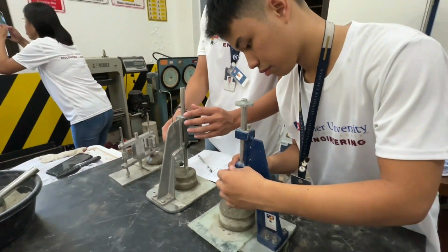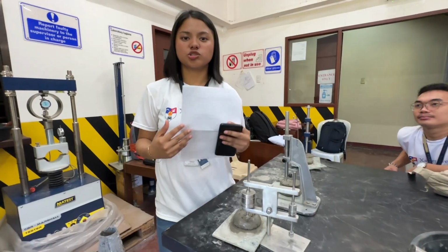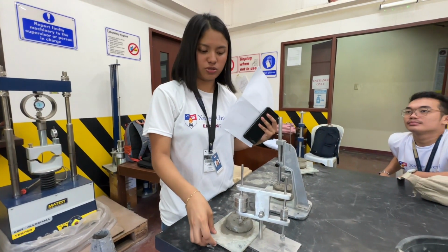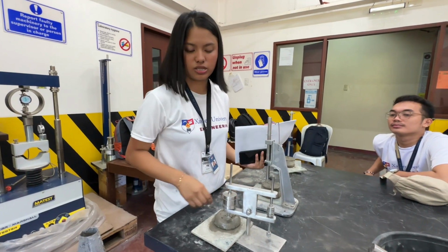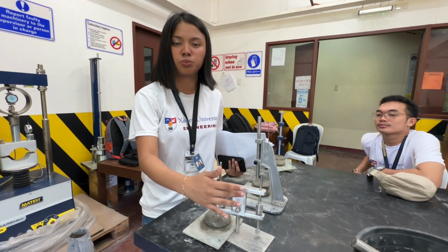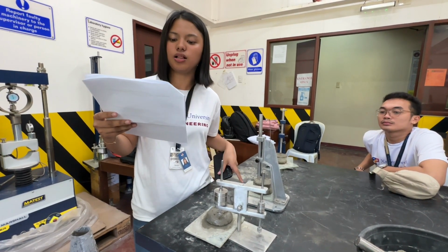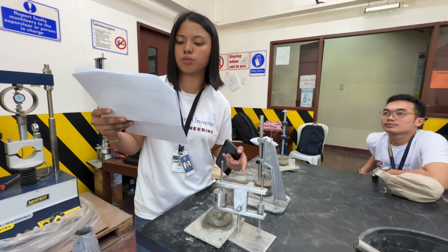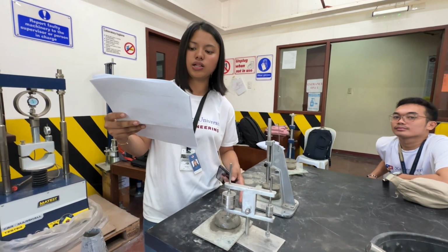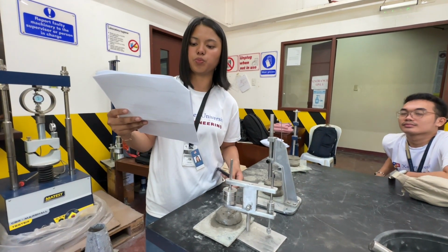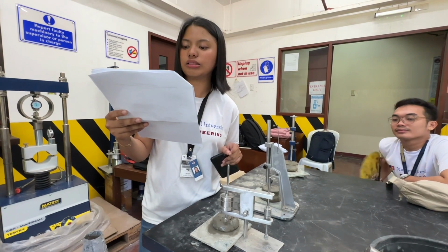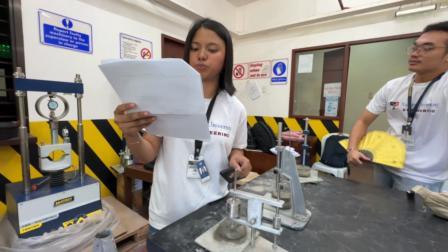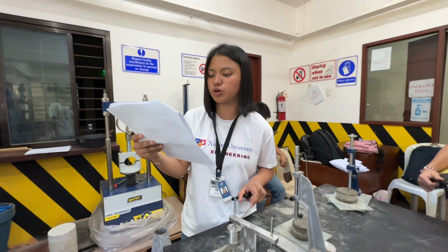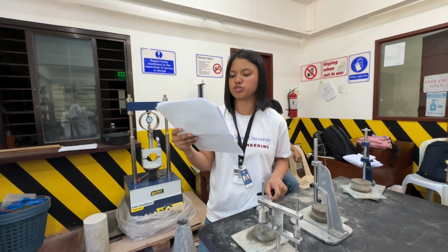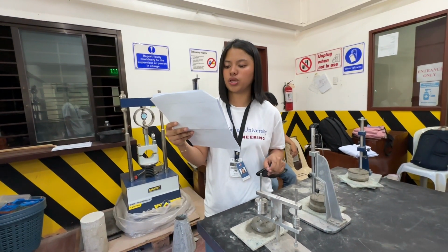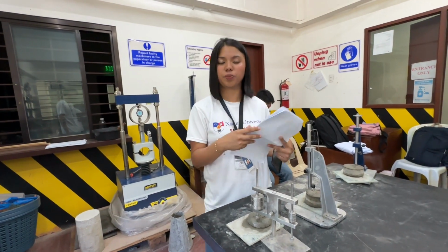So here we have a different sample, which is different from the Vicat needle. It doesn't have any mold and it is measured through the Gilmore Apparatus. So same with the Vicat needle, we place the molded paste and excess paste under the Gilmore Apparatus. So using the Gilmore needle, we determine the Gilmore initial time of setting as the point with the first penetration measurement that does not mark the specimen surface with a complete circular impression. Verification measurements must be obtained within 90 seconds of the first initial set measurement. So to find the Gilmore final set, we're going to repeat steps 3 and 4 and record and interpret the data.